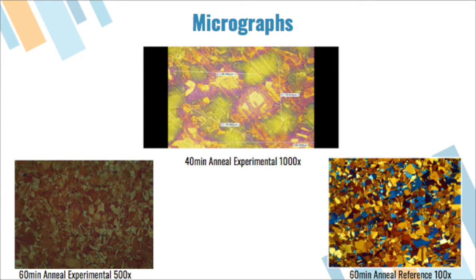As we see here, the image is quite interesting. There are a multitude of possibilities resulting in this feature, and keep in mind this is at 1,000 times magnification. First off, it is plausible that the sample had grit contaminants. After grit is used long enough, it becomes possible for it to accumulate on the object that is being polished. Thus, if this happened early on in the polishing cycle, it had time to cling to the surface where a cleaning solution would not be enough to rip it off. Another, less likely scenario could be an oxidation layer at the surface, but we did not see this on any other sample, so this is unlikely.